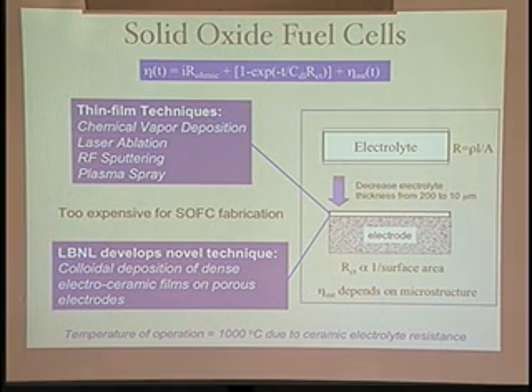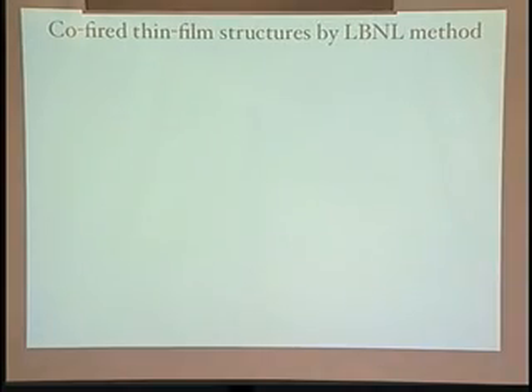In some sense, it took us a while to get there, but it's very simple. We call it colloidal deposition. And we can make all sorts of electroceramic films this way. And it goes like this. You start off with an electrode. Now, the electrode for an SOFC is typically nickel. So you start off with nickel oxide, because when it's in the hydrogen environment, it'll be reduced to nickel metal.